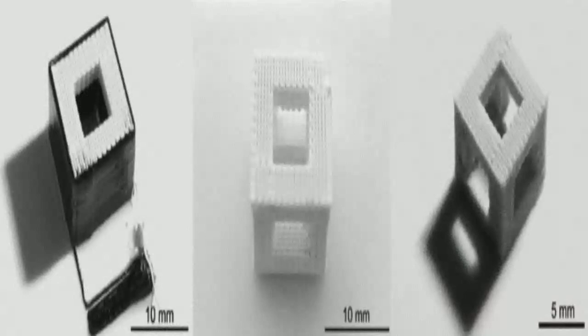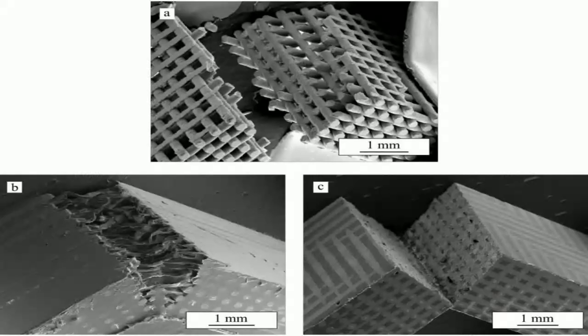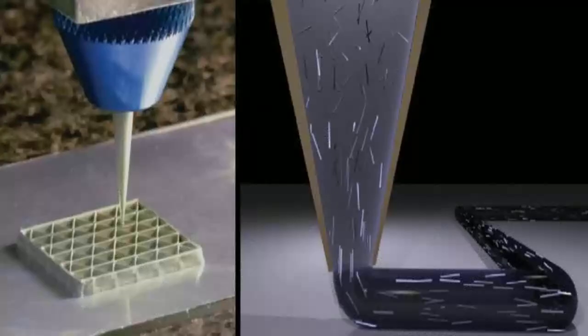Different ways to get it to solidify. Researchers have experimented with ways to speed up that solidification, like freeze-form extrusion, where the extruded paste is immediately frozen on a cold plate. Clever? Or another one called ceramic on-demand extrusion, where they incorporate drying agents or use heat to help the layers stiffen faster. It just shows the core challenge, right? How do you get that printed structure stable right away. And this is where we get into the fascinating world of rheology.